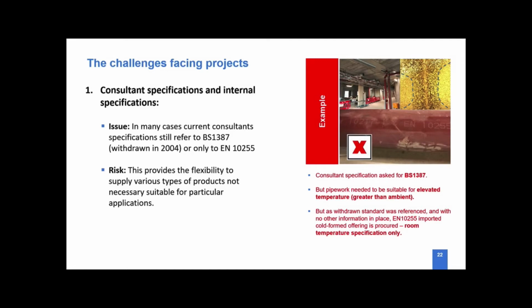And the example we've got here is from one of the projects where the consultant specification asked for BS 1387, which was basically incorrect. But the requirement was that pipework needed to be suitable for elevated temperature, which is greater than ambient. But obviously, as a withdrawn standard was referenced with no other information in place, the supply chain referred to EN 10255, but unfortunately defined the cold form tube instead of hot finish, which obviously was not compliant with the project requirements.